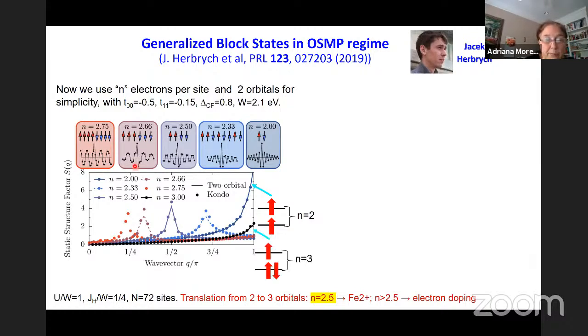So when we come back to n equals 3, now we have an integer number of electrons per side. We get effective spins 1/2 that again order antiferromagnetically, so we get again the peak at pi. This is a very interesting behavior that occurs in this orbital selective Mott phase.